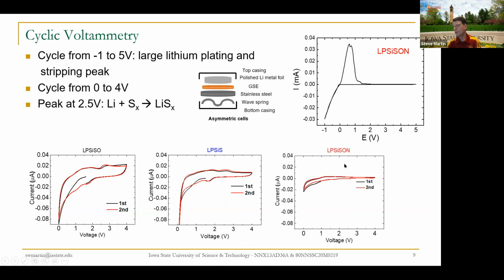And then when we go to the oxysulfide nitride, this is microamps, so this is 20 nanoamps. That's very low current. You can see there's almost no electrochemical activity. It's just basically a straight line, showing that in fact the glasses are very insulating to electrons, but very highly conducting to ions. And so the oxygen and nitrogen suppress these side reactions, because of course we don't want the battery to sit there and react. We want it to be perfectly stable, and we only want it to react, as it were, when we draw on the battery.